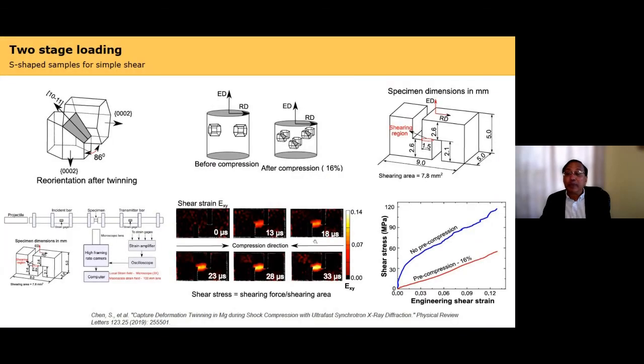We also did experiments on the pre-compression of the sample. When you pre-compress the sample, then the strength you observe in the split Hopkinson bar experiments, using an S-shaped sample, is lower than when you have no pre-compression. This also explains why our strength at high pressures is lower than in the split Hopkinson pressure bar experiments. So there's some rich physics in inducing anisotropy due to shock and then shearing the sample. We are still trying to understand these mechanisms.